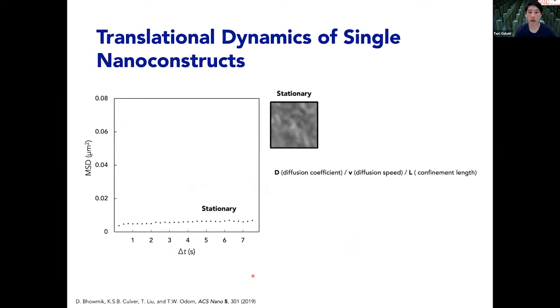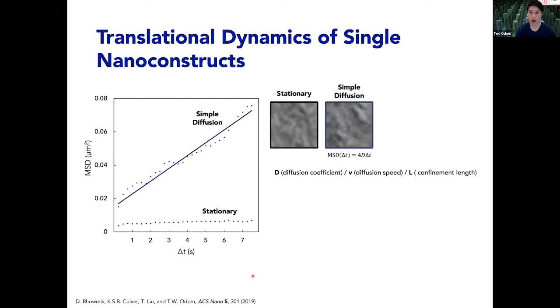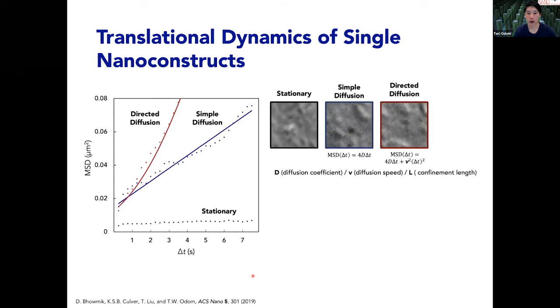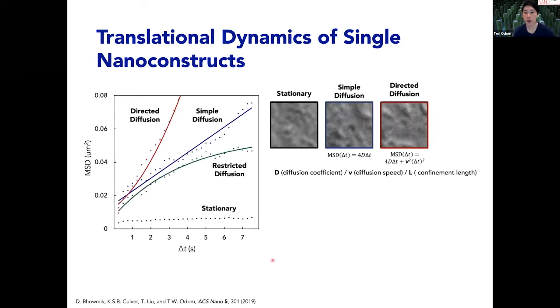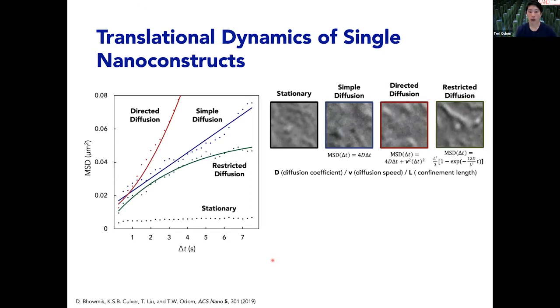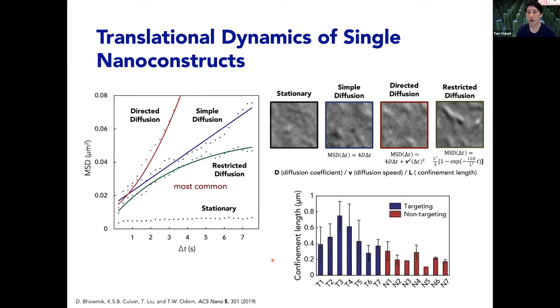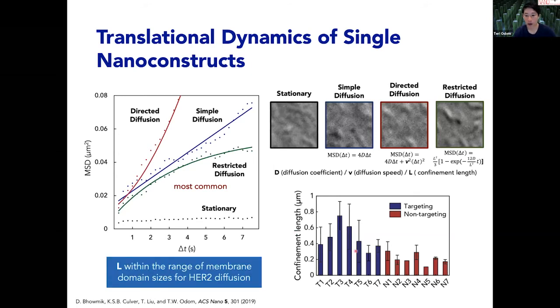So we looked at the different translational dynamics, and we can categorize them, or we could fit them to standard diffusion related effects, where either the particles are stationary or they're simple diffusion, or directed diffusion, or even restricted diffusion. And so the most common type of motion is restricted, partly because there are a range of different contributors on the cell membrane. There's matrix involved. There are other types of proteins involved, and so it's trying to translate in this very complicated system. But what's interesting here is that if we look at the confinement length of these targeting particles for the non-targeting, this confinement length L is within the domain. It's similar to the domain sizes for HER2 diffusion.